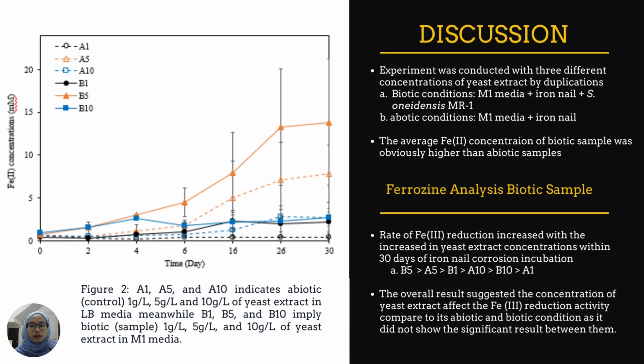Ferric reduction activity was monitored via ferrozine assay to quantify the dissolved ferrous ion incubated with iron nail in M1 media with different concentrations of yeast extract within 30 days of iron nail corrosion assessment. B5, referring to biotic samples supplemented with 5 gram per liter yeast extract, shows the highest increment in ferrous concentration compared to the abiotic sample A1 supplemented with 1 gram per liter yeast extract.